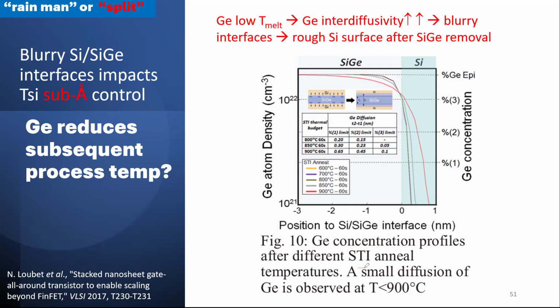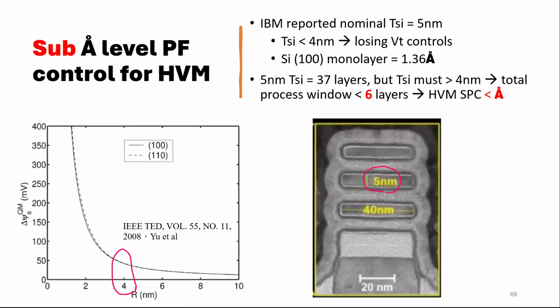Because you cannot put perfect oxide there. You have to use some kind of CVD process. And you do some kind of liner to oxidize the trench. And then you stuff it with some easy oxide because it gets you high aspect ratio. And you anneal at high temperature. So there are multiple anneals, many anneals. High temperature process in STI. Once you finish that, you'll find some diffusion of germanium going in. Because we have how many layers? We need to control 6 monolayers. I mean that it's not just at the moment you're manufacturing it, but also afterwards. That's the tricky part. Okay. That's the tricky part.